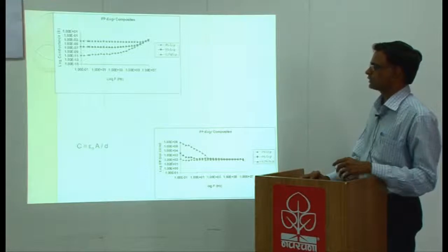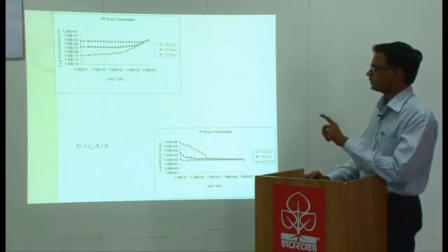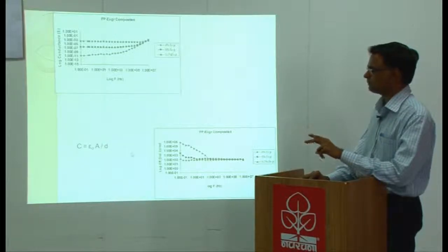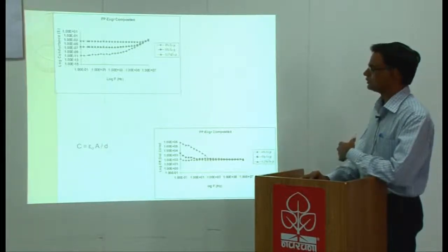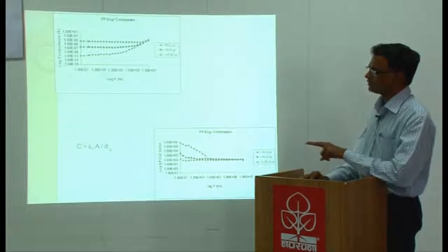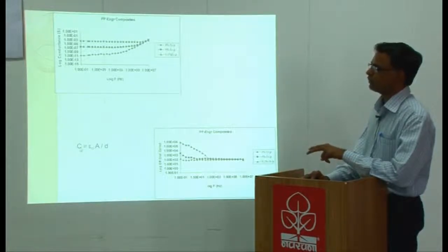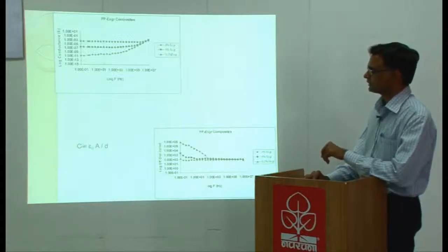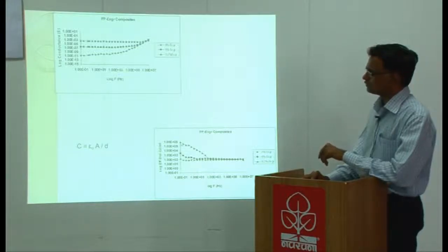This could be understood because expanded graphite particles can be thought of as a parallel plate capacitor. The more the concentration of fillers you have, the inter-particular distance is reduced because eventually it results in increasing interfacial or inter-junction capacitance which is reflected in higher value of effective dielectric constant at low frequency.